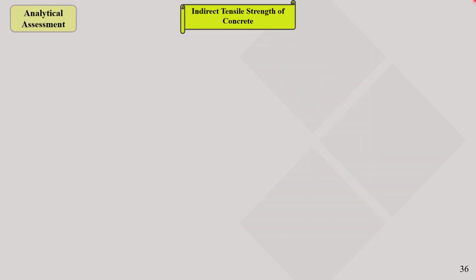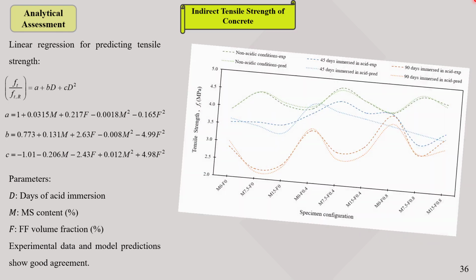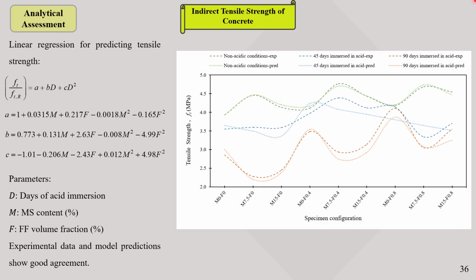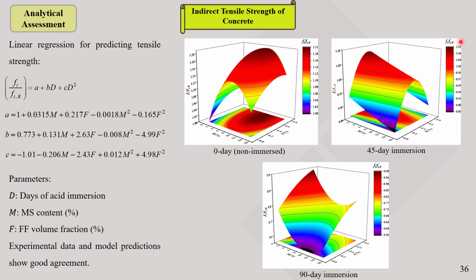An analytical evaluation was also performed for tensile strength, and an analytical relationship was developed. The comparative graph of experimental data and the model shows good agreement. Response surface plots are provided for the 0-day, 45-day, and 90-day conditions. FT represents the tensile strength of the samples, and FTR indicates the tensile strength of the reference sample under non-acidic conditions.